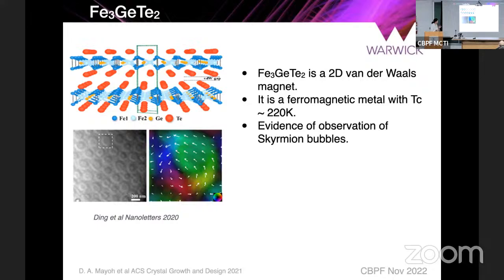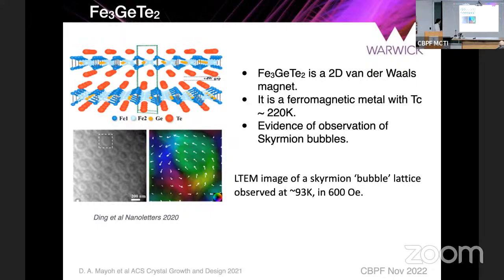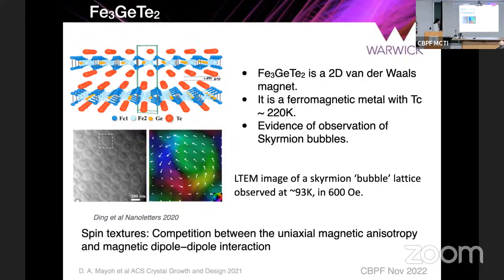And what was more exciting was that there was some evidence of the observation of skyrmion-like structures, and they called them skyrmion bubbles. And this was observed by a group in the US associated with IBM, and they did what's called Lorentz transmission electron microscopy. So for those of you who are not familiar, this is a technique that's used to actually image these skyrmion lattices in these materials.